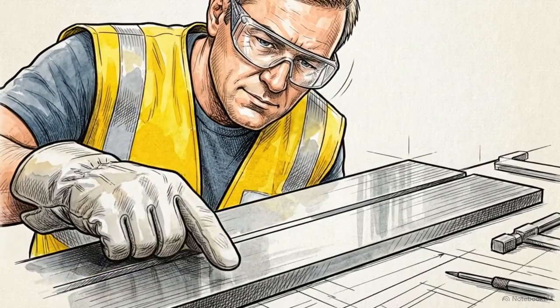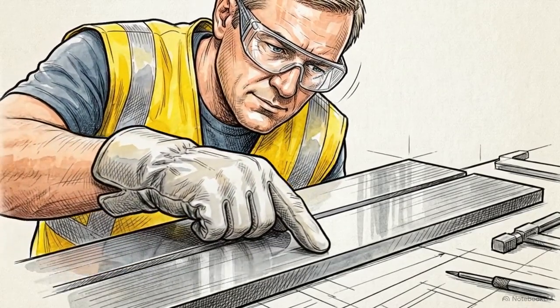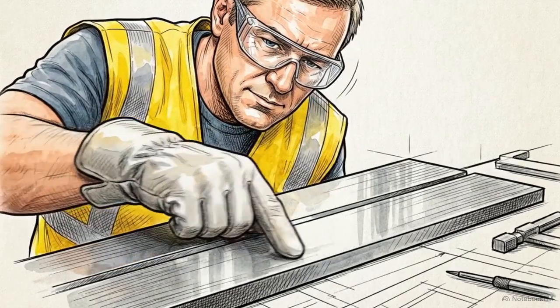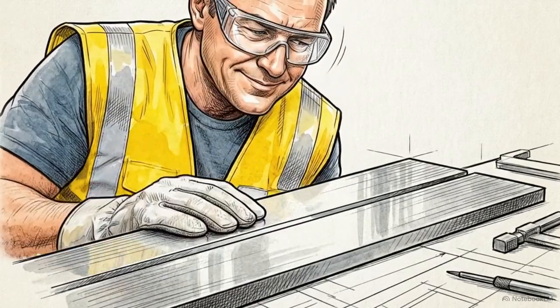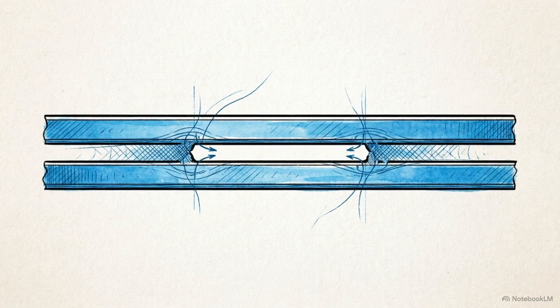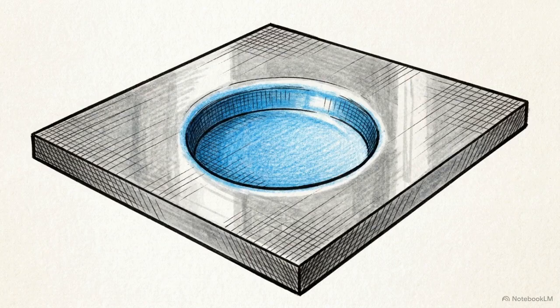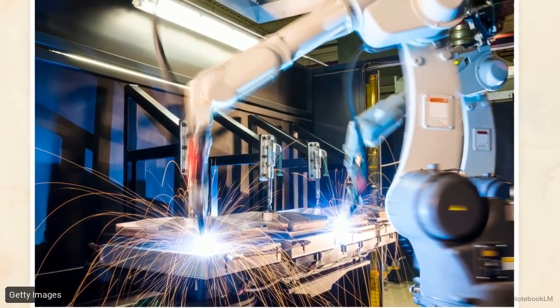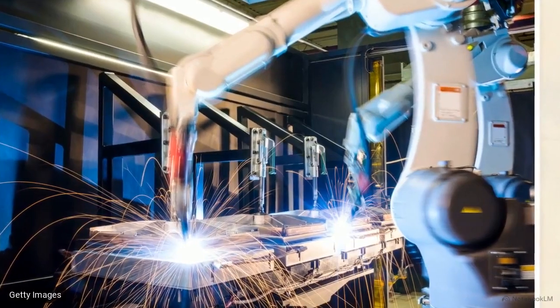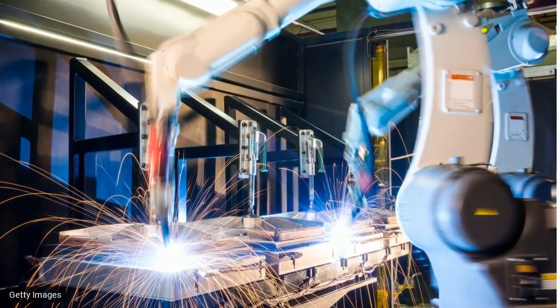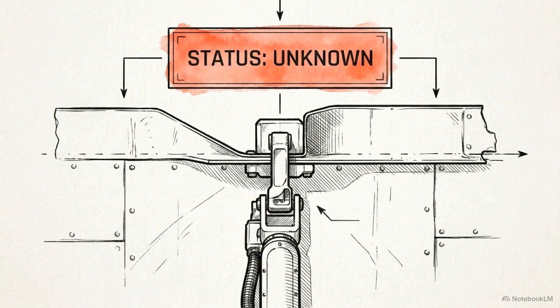What terrifies quality engineers is that an undersized nugget or a cold weld can leave a clean surface on the exterior of the sheet metal. The joint looks acceptable, entirely hiding a failure from the naked eye. The rule of resistance spot weld quality control is that visual inspection of the exterior surface cannot verify structural integrity. The automation we rely on is unthinking. A robotic arm blindly executes the code and current you give it. It cannot verify the hidden thermodynamic reality occurring between the metal sheets.